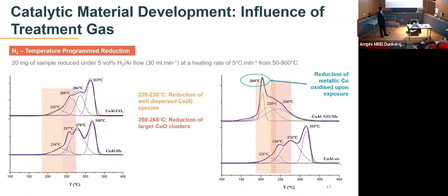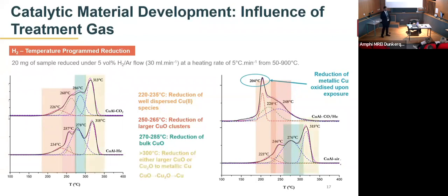The second temperature range that we see here is 250 to 265 degrees Celsius, which is generally associated with the reduction of copper oxide clusters. The next, at a higher temperature of 270 to 285 degrees Celsius, is generally the reduction of bulk copper oxide. And finally, the reduction temperature above 300 degrees Celsius is ambiguous. Some authors suggest this to be the reduction of larger copper oxide species, or the reduction of Cu2O which has been formed from the reduction of CuO. So we have a two-stage reduction from CuO to Cu2O, and from Cu2O to metallic copper. Either of these possibilities could take place in our case.